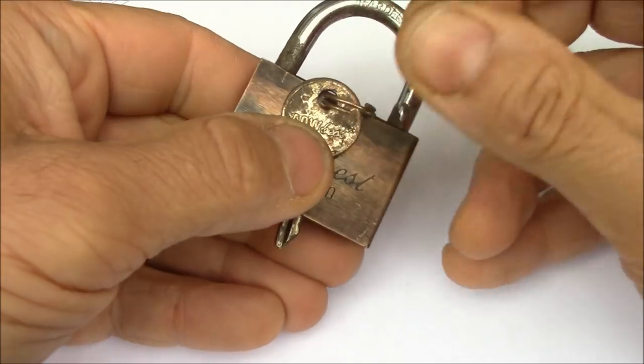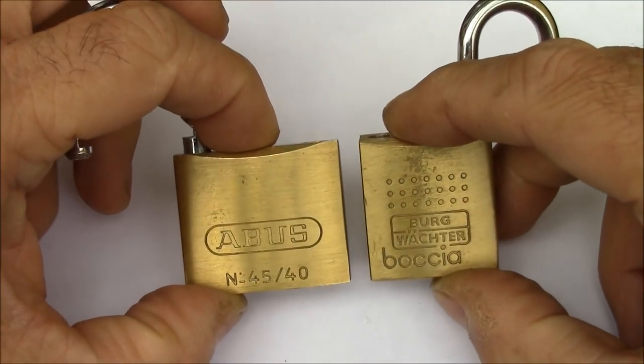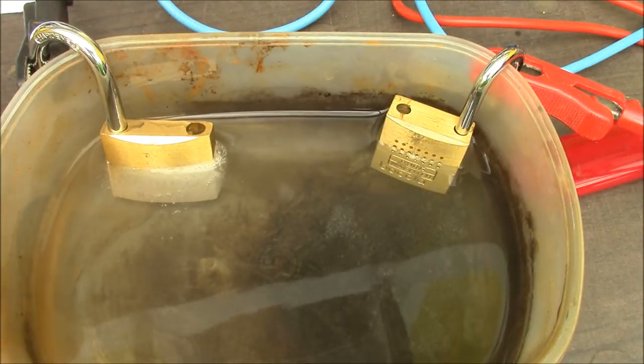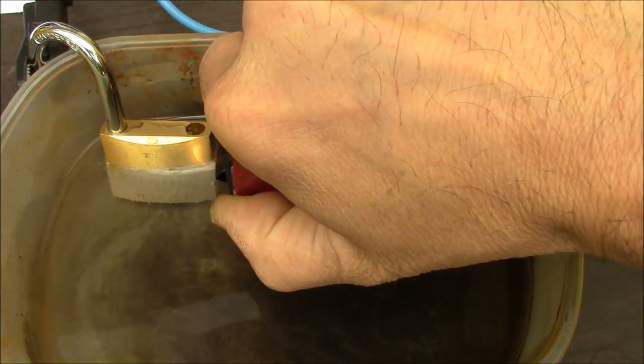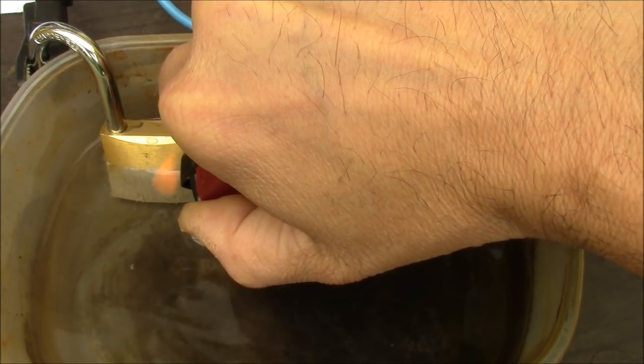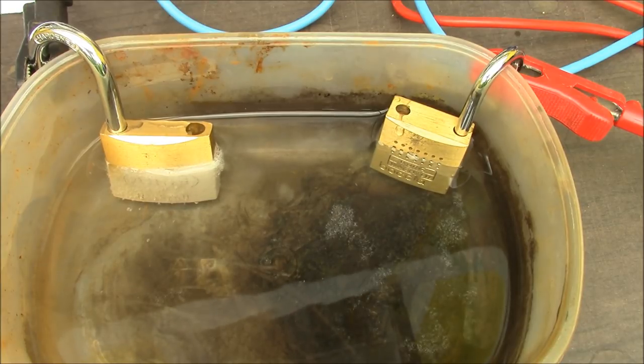I want to see what happens if on both sides of the cathode and anode we have a brass lock. I have two examples I want to use for that experiment. While the electrolysis treatment for the first lock was to get rust off the shackle, this experiment with two brass locks is just to satisfy my curiosity. I've seen from the first experiment that the steel bolt on the anode lost some material, so I'd expect the brass lock on the anode to lose material too. As zinc goes more easily into solution, I'd expect that lock to become a little reddish from the remaining copper. But let's see what happens.